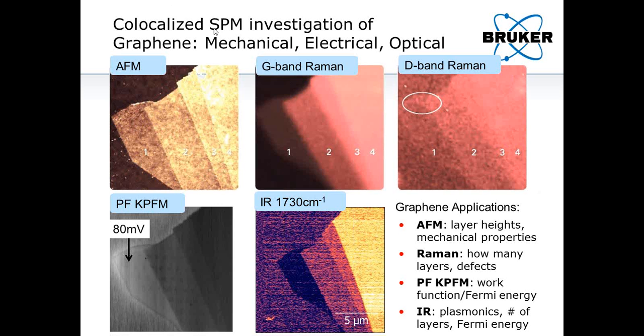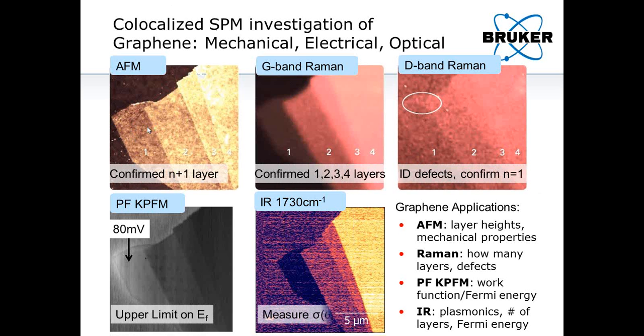So, of course, in the top left, I show some AFM height data, which is going to confirm that we are stepping in exactly 1 layer steps. But I also show this G-band Raman data, which allows us to confirm using the G-band frequencies that we obtained how many layers we have.